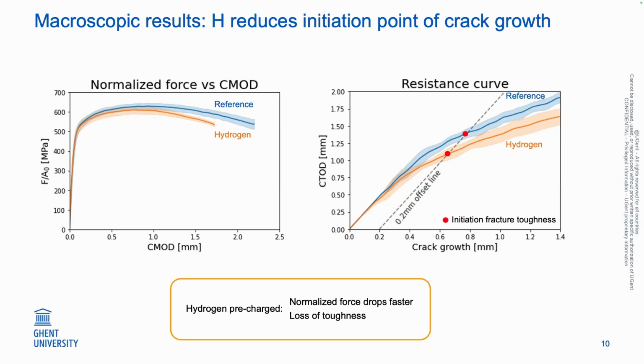Maybe more interesting is if we look at the resistance curve. There's one point that is interesting for us. It's the initiation point. And we see that even with the existing tests, we already have a drop of the toughness at the initiation point of the crack growth.